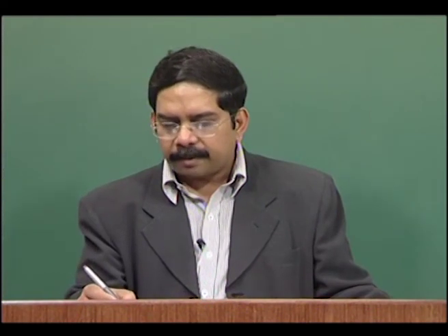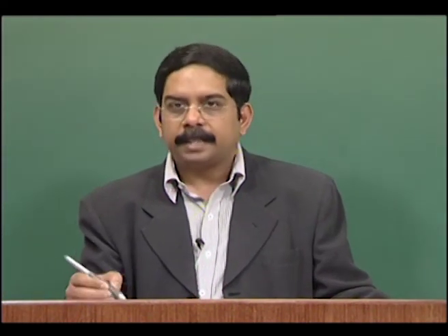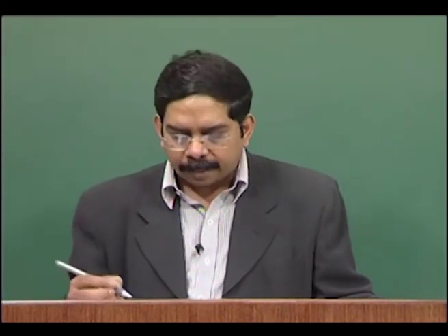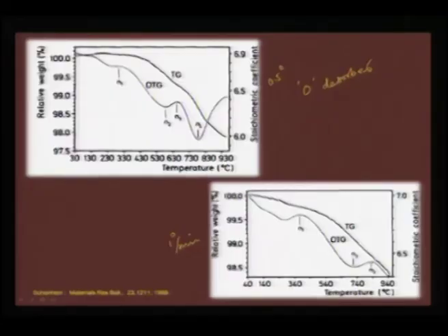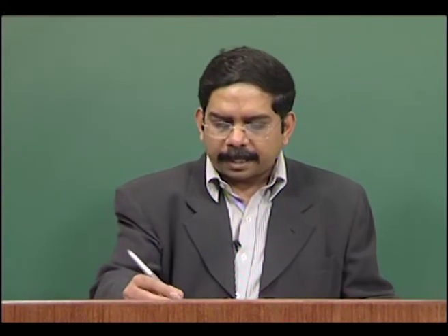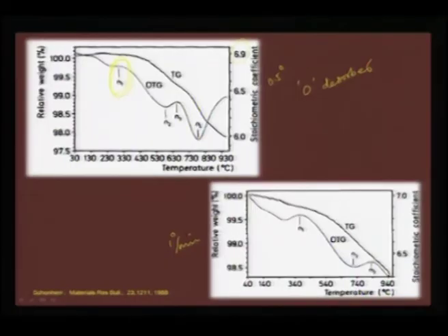We cannot control the 730 degree C because it is at high temperature. Therefore, it is important, if we need to achieve this 6.9, we need to be very careful to anneal this compound at 330, because that is where the oxygen exchange is happening. So, any sample which is prepared before we measure the superconductivity, you need to make sure that there is a post annealing that is done at around 300 degree C for a long time, so that enough oxygens are getting incorporated into the lattice, and that is what we see.